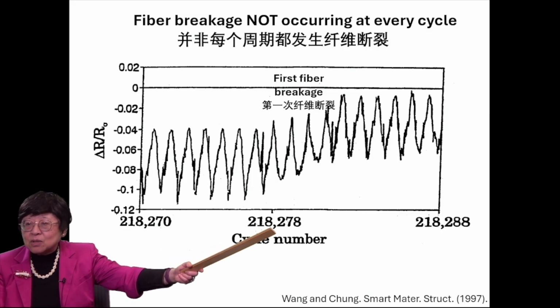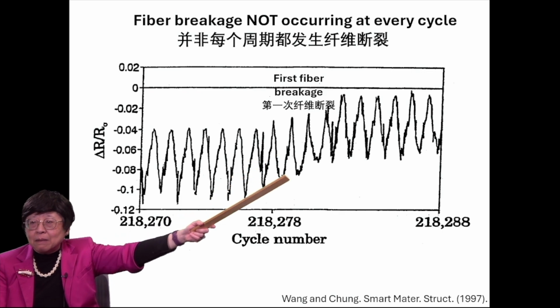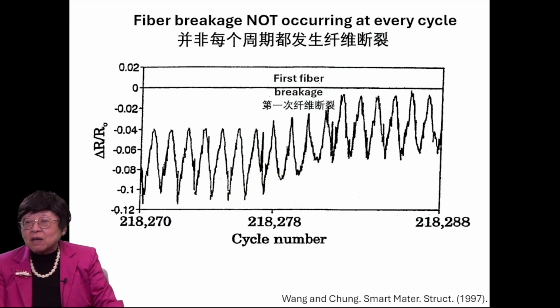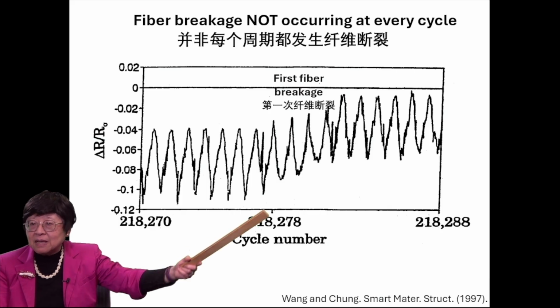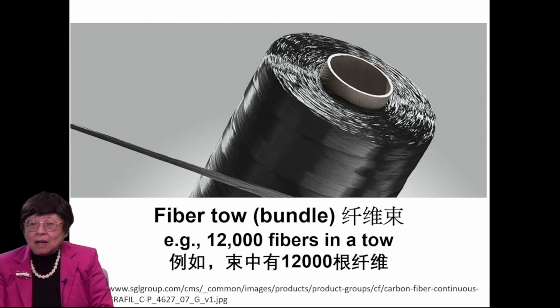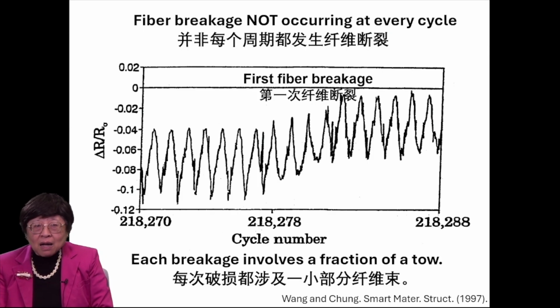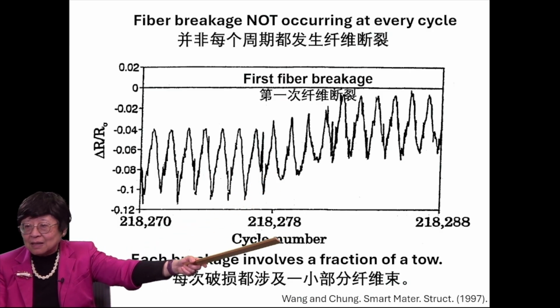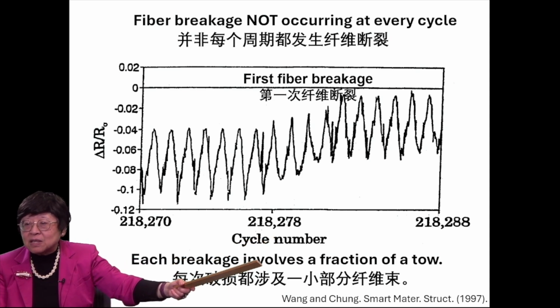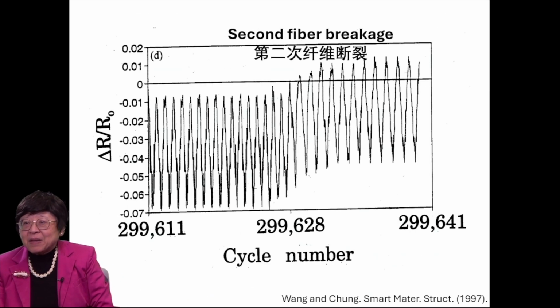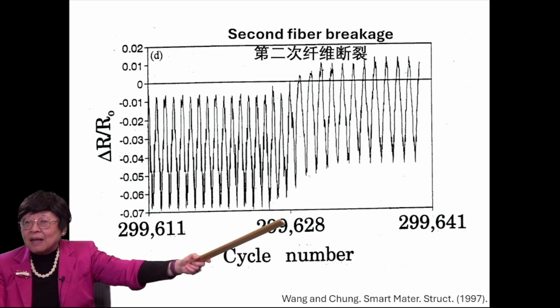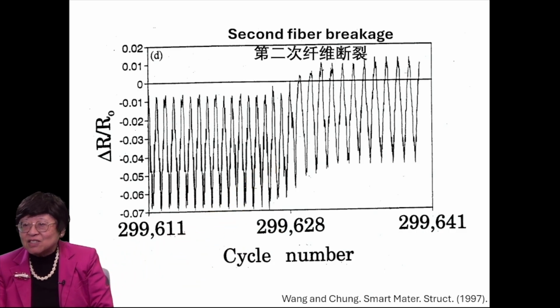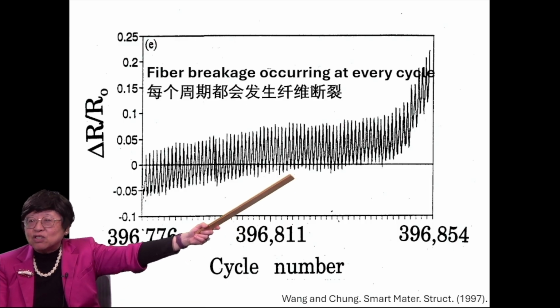After so many cycles, we see the first increase in the baseline of the resistance, and that is because of the first occurrence of fiber breakage. Note that the fiber breakage does not occur at every cycle, but in spurts. Now, a fiber tow means a fiber bundle, such as 12,000 fibers in a tow, and the composite involves fiber tows. And this is the second time of fiber breakage occurring at this high number of cycles. Each breakage involves only a fraction of a tow. And this is still later, at a larger cycle number. And here, this is the second fiber breakage. And still later, we see fiber breakage occurring at every cycle.